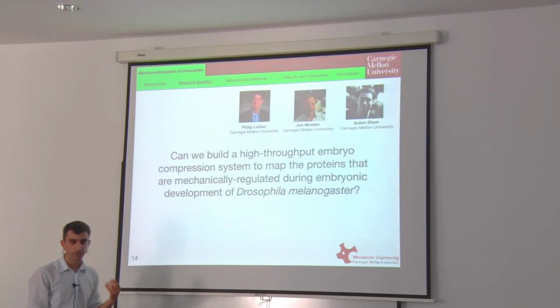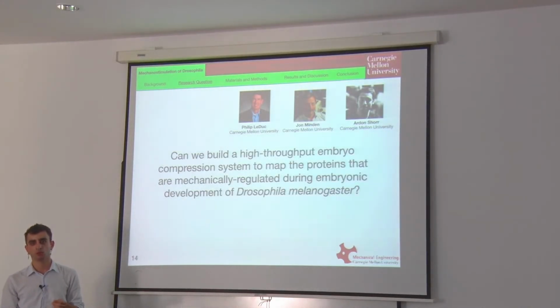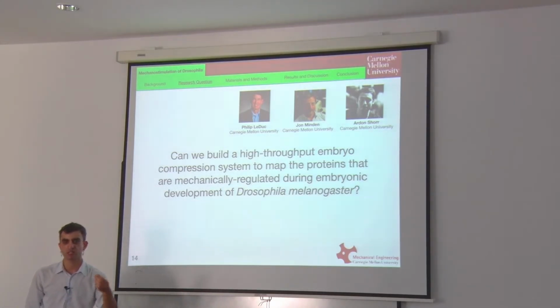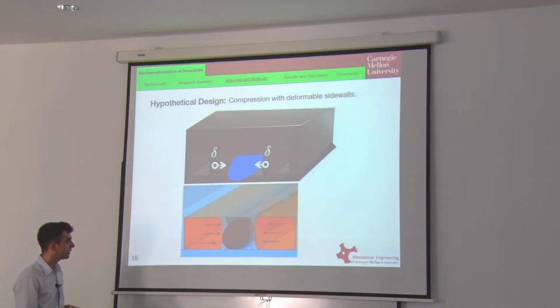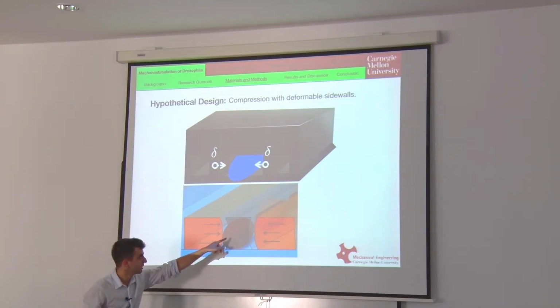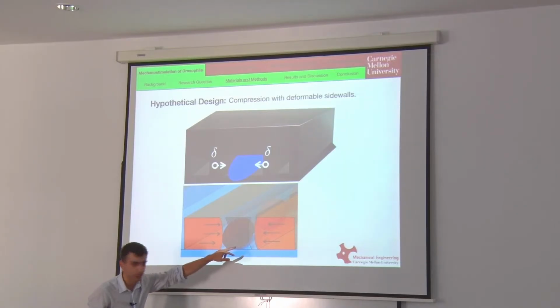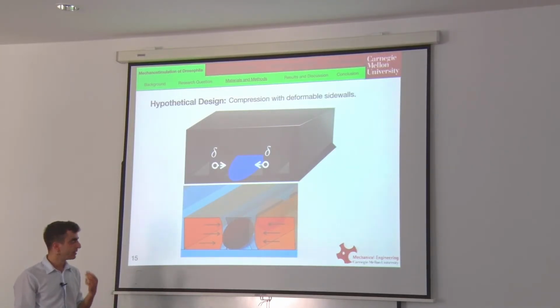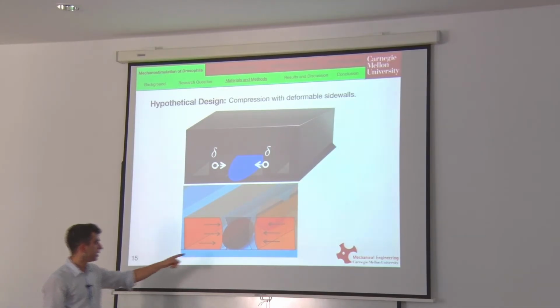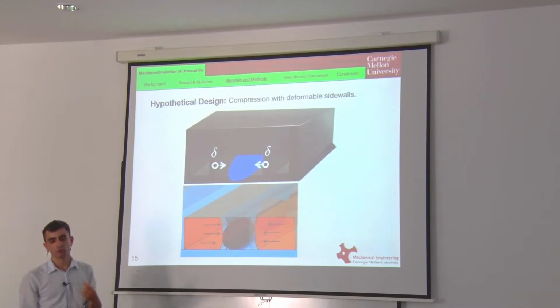So what we thought is, if we can make a system that can precisely apply mechanical compression to fruit fly embryos to see which proteins and genes are being activated at the end of this mechanical stimulation, and we want to do it for hundreds of fruit fly embryos so we can get statistically significant results. And this is the microfluidic system that I came up with hypothetically. So there is a center channel where we put the embryos. The center channel has 2 side channels on each side, which are gas channels, and they are dead ends and pneumatically activated. And in between, there is a deformable sidewall made out of PDMS, which can be deflected inwards if you apply positive pressure and outwards if you apply vacuum.